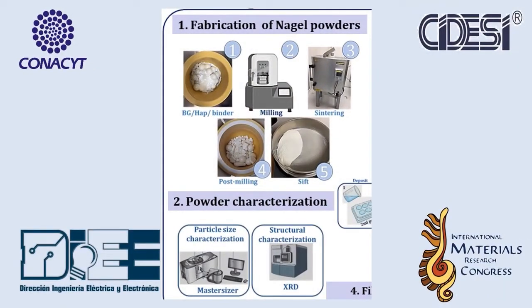The first step of this research involved the synthesis of Nagelschmidtite powders, which were fabricated following the methodology of our research group, which consists of a mixture of hydroxyapatite and bioactive glass as the precursor powder using high-energy mechanical milling. Then a sintering process is performed, where the phase is obtained. After the sintering, a post-milling process is carried out to homogenize the particle size. Finally, the powder is sieved to obtain a particle size below 53 microns. The powder obtained is structurally characterized by X-ray diffraction and laser diffraction to determine the particle size.